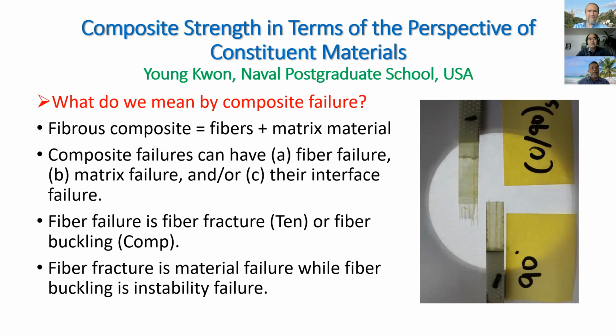Of course, we are talking about the long fiber composite, but it could be short fiber or discontinuous fiber, or sometimes woven fabric composite. But in any composite, if you look at the failure at the constituent material level, such as fiber and matrix material level, then we can say that those failures could be classified into three different modes. One is the fiber failure, second is the matrix failure, and the last one is fiber matrix interface failure. So, for example, if you apply the loading along the fiber direction for unidirectional composite, then mostly the matrix failure is going to initiate, followed by interface failure, and then eventually fiber failure.